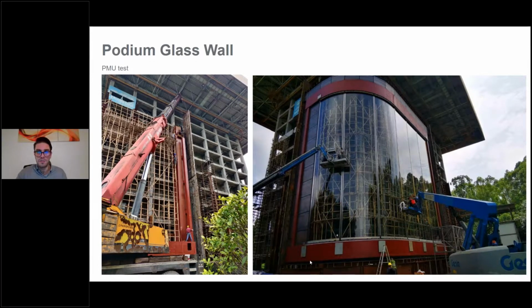So this test was carried out not only to water tightness test, air tightness test, but there was also some structural tests, clearly with wind load applied up to 1.5 times the design load. So we were basically blowing up to 5.3 kPa of wind on the facade.